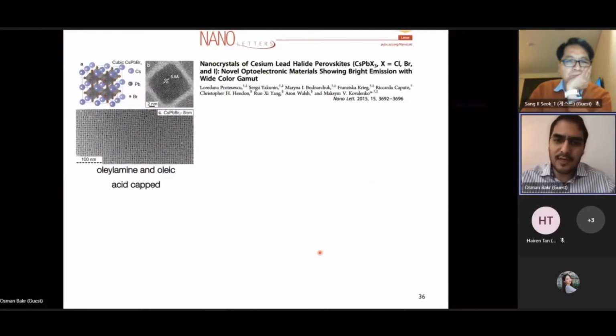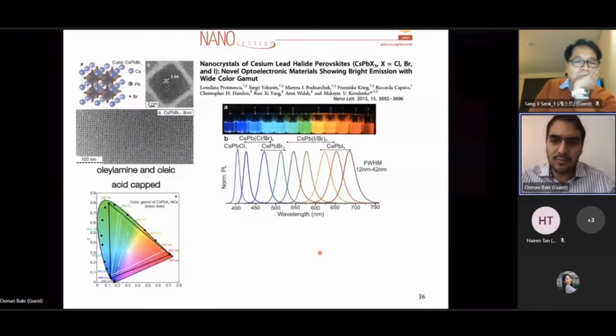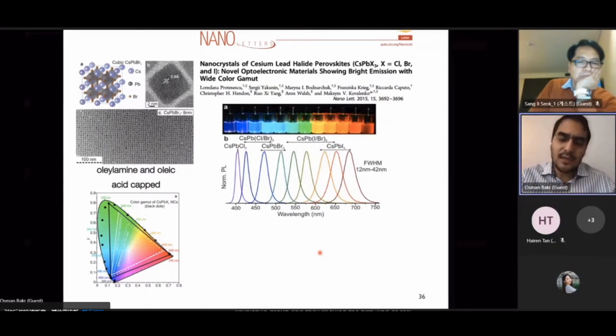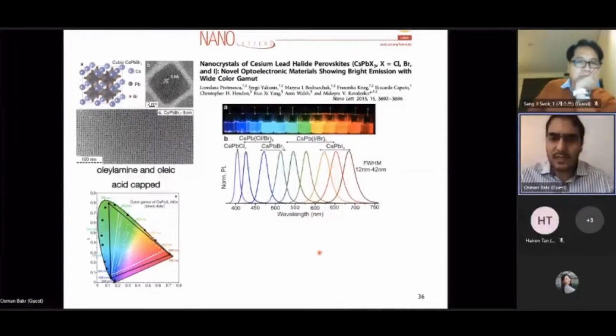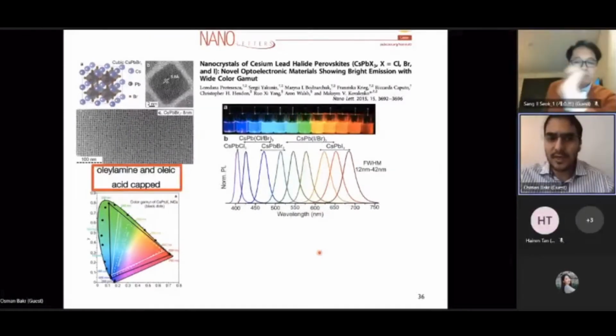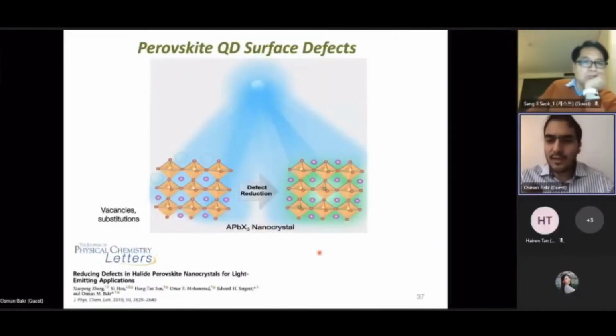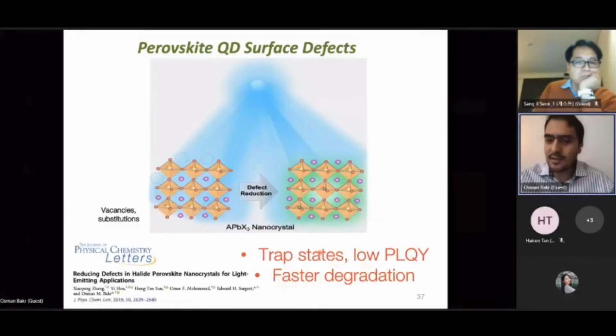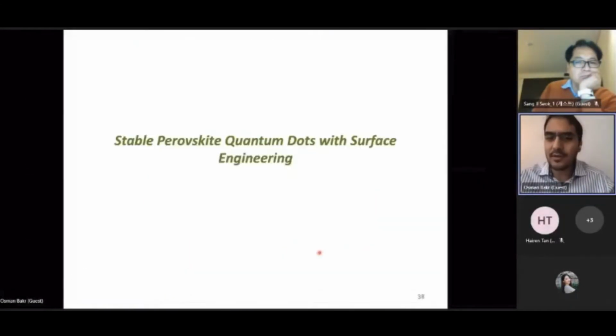So perovskite nanocrystals, or sometimes quantum dots, were first introduced by Kovalenko's group, and they showed that these materials can be tuned. Their color can be tuned by changing the halide composition, and you had a monodispersed solution of perovskite nanocrystals. But they were capped with oleic acid and oleylamine, and that turned out to cause defects on the surface, because oleic acid and oleylamine caused an acid-base reaction that degraded the surface and eventually caused trap states and degraded the photoluminescence of the nanocrystals.